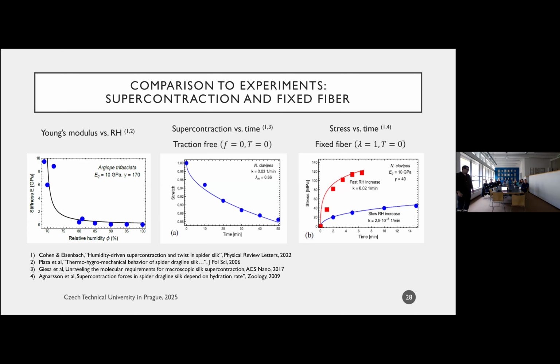And so we compared it to a wide array of experimental results. Let me show you a few. So again, what you see here is Young's modulus as a function of the relative humidity, right? So you can see here, we get a pretty good fit with the trend for the stiffness. In this experiment, what they've done is they took a spider silk fiber, they just held it on one end, no forces applied, they increased relative humidity and saw how it contracts as a function of time. And so again, you can see that we capture this trend.